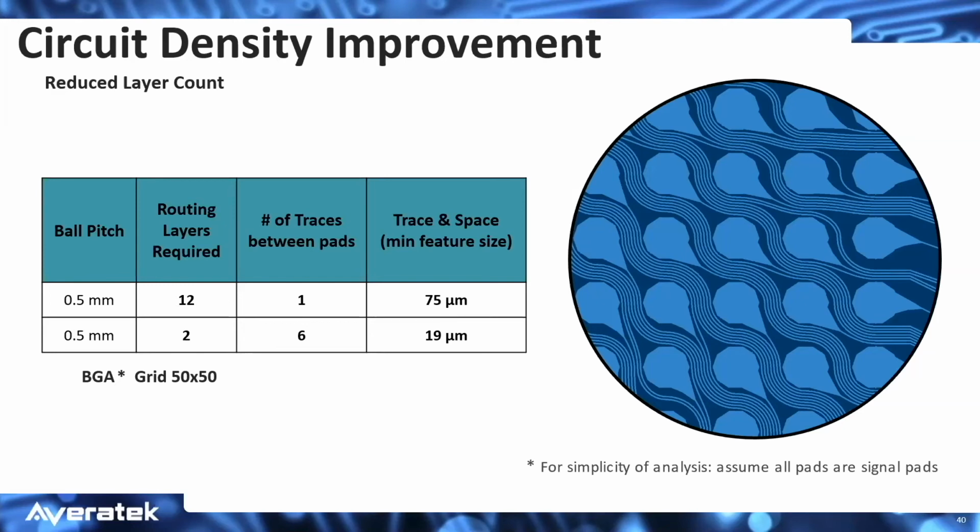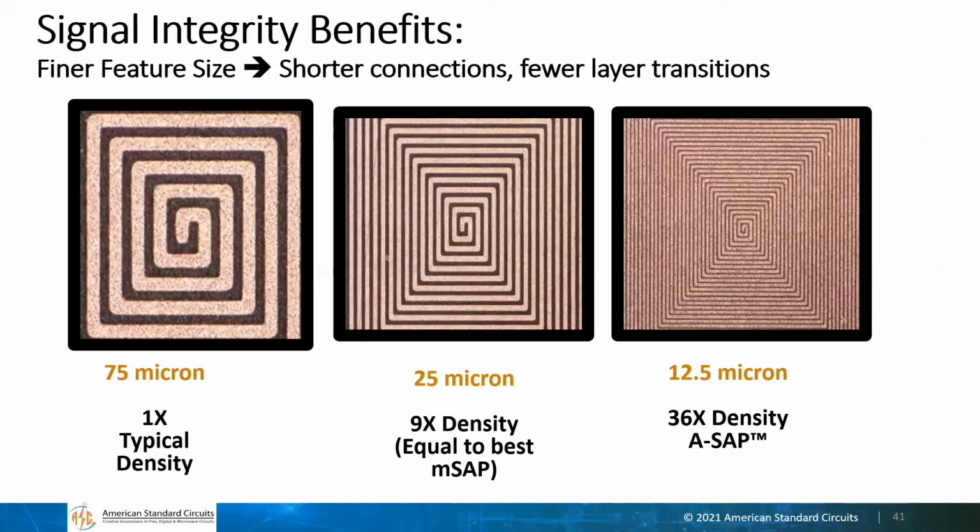This is an image that we got from the Navy. The Navy is one of our licensees. They've got a facility in Crane, Indiana. And they were etch limited at first, subtractive processing. You can see that 75 micron spiral on the left. They do have a MIVA lithography tool that had both, I think, a 25 micron head and a 10 micron head on it. They were able to get down to 25 microns within the first few weeks of having our process.